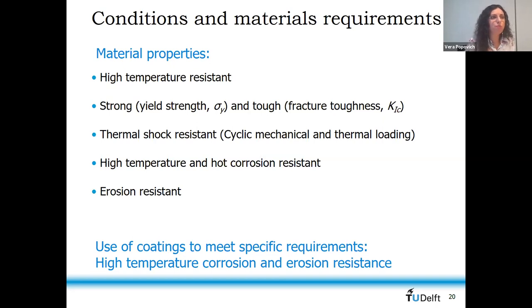because often we see that blades these days are proposed like ceramics, for example, or intermetallics. You should know for sure that they are not as ductile, so their toughness is not high compared to metals. But not all areas in the engines require high toughness resistance. So if there is no danger of impact of a certain object or something, then a different threshold of toughness can be put upon that material.